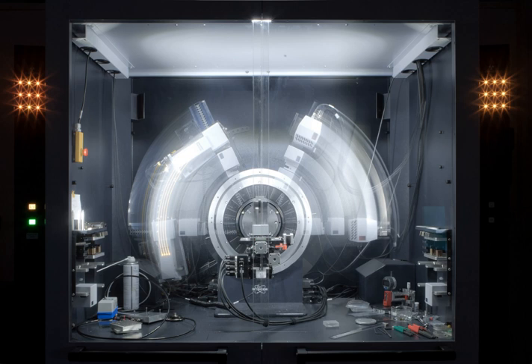The solution conditions that favor the first step, nucleation, are not always the same conditions that favor the second step, subsequent growth. The crystallographer's goal is to identify solution conditions that favor the development of a single, large crystal, since larger crystals offer improved resolution of the molecule. Consequently, the solution conditions should disfavor the first step, nucleation, but favor the second, growth, so that only one large crystal forms per droplet. If nucleation is favored too much, a shower of small crystallites will form in the droplet, rather than one large crystal. If favored too little, no crystal will form whatsoever.